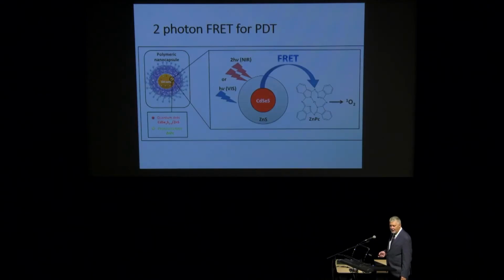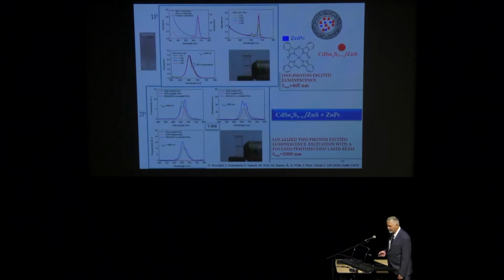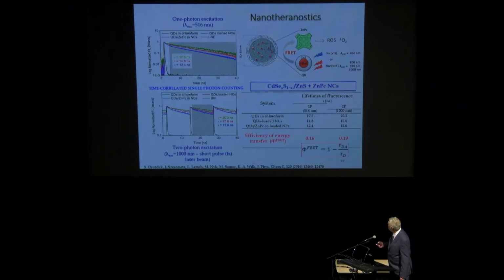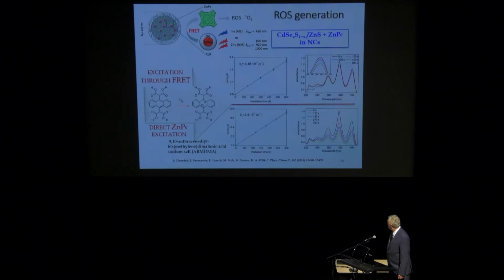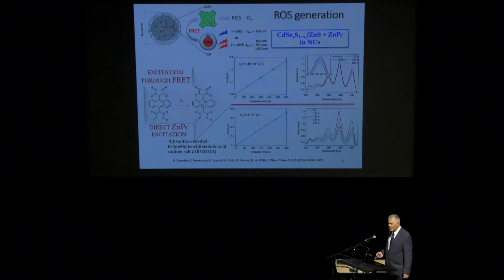And, well, we have this energy transfer. We can prove that using certain spectroscopic techniques. This is one of the examples that by measuring the lifetime of the luminescence, we can prove that there's energy transfer going on. And the efficiency of this energy transfer was not extremely high, around 20%, but it's a beginning. And we can also prove that indeed, reactive oxygen species are being generated. One simple way of doing that is by using a probe like this one, which is oxidized by singlet oxygen, and then its absorbance decreases, so we can follow this change of absorbance to calculate how much singlet oxygen we are generating here. So yes, this sort of an approach works.